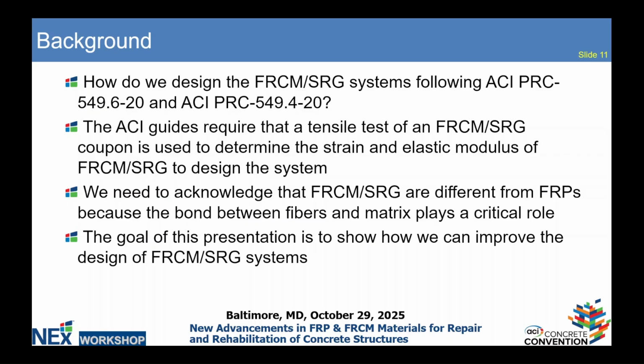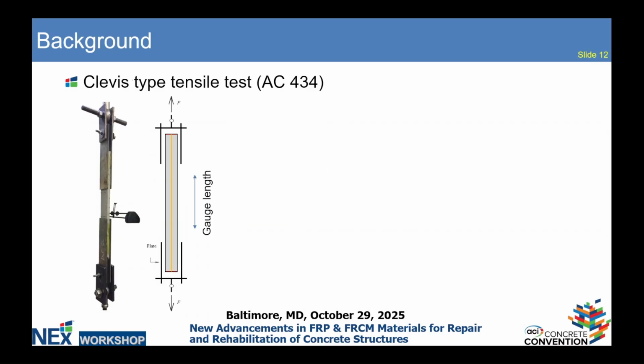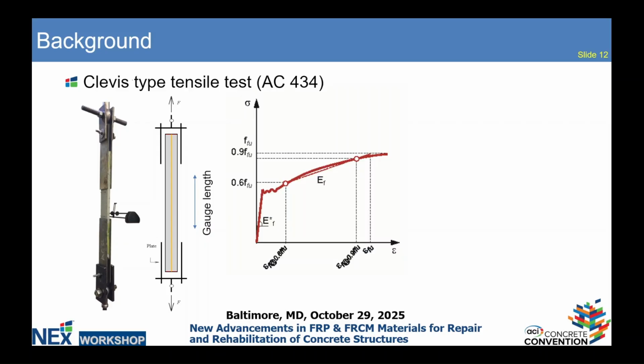So this is a classical picture of the test used in ACI, which references AC434, a document from ICC. And the idea is you see the coupon with the fibers in the middle of the thickness, and then you glue two plates at each end, and then using a Clevis type connection, you're pulling basically the plates through bond transfer to the matrix, and you're obtaining your response of the tensile test. This is a typical response. You have initially the cracking of the mortar, and then eventually the fibers will pick up the load.